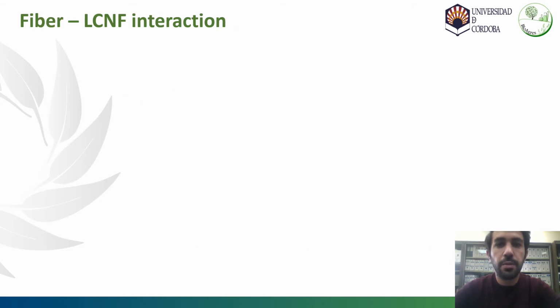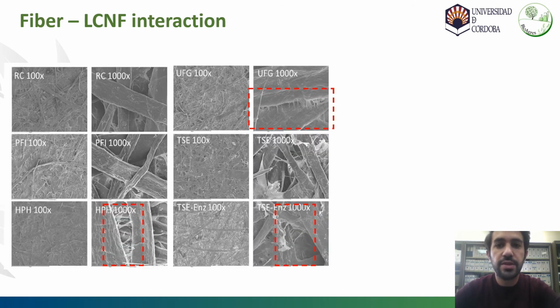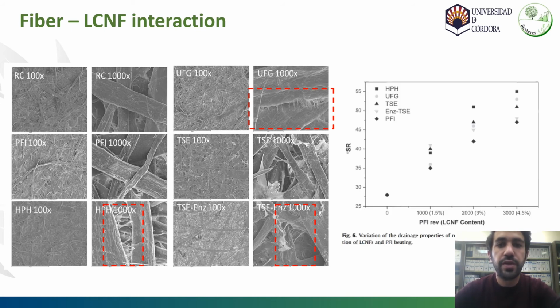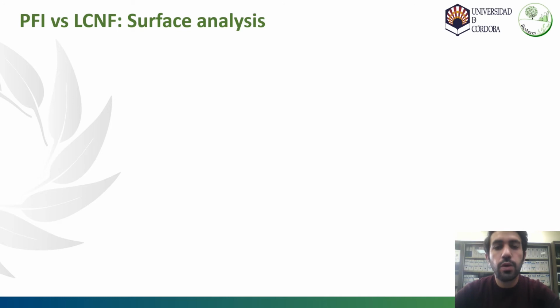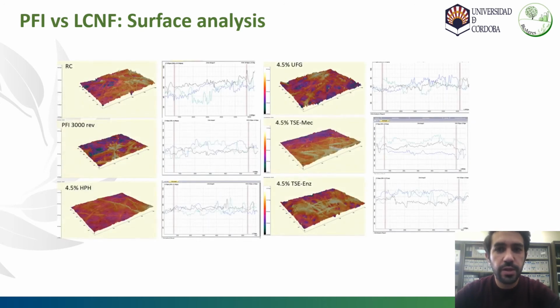In the microscopic image, we can observe the effect that these lignocellulose nanofibers produce between the fibers to exert the reinforcing effect and the interaction that we were talking about. We can also observe that as the nanofiber content or the intensity of the refining increased, the resistance to drainage increased due to the greater interaction with the medium where the nanofibers are added, and the surface area of the fiber increased during the refining.